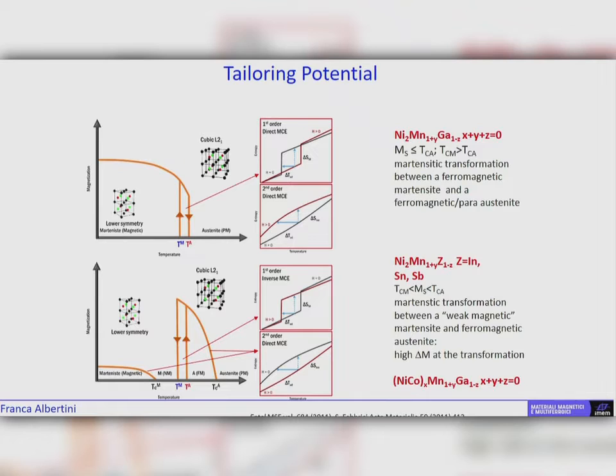First, a low magnetic martensite, then we have no magnetic moment, and then by increasing temperature, in this case, we have an increase of magnetic moment. So we can tune this huge change of magnetization from 0 to the maximum or the opposite by temperature and by changing the composition. Here, for instance, in these diagrams, there are entropy versus temperature plots, and in correspondence to this transition, we have magnetocaloric effect. In this case, it's a direct magnetocaloric effect at the first order transformation. Here we have an inverse magnetocaloric effect at the first order transformation, followed by a direct magnetocaloric effect at the Curie transition.